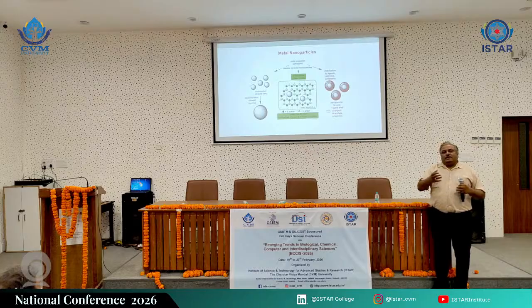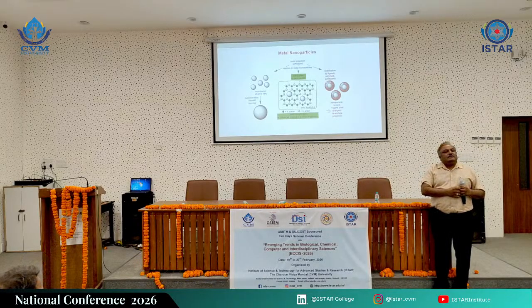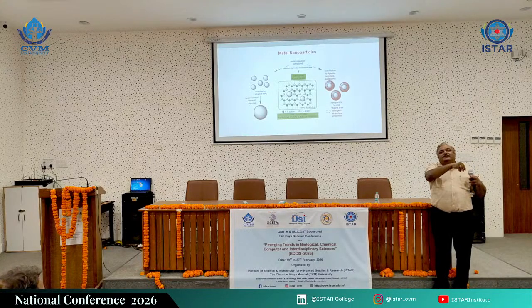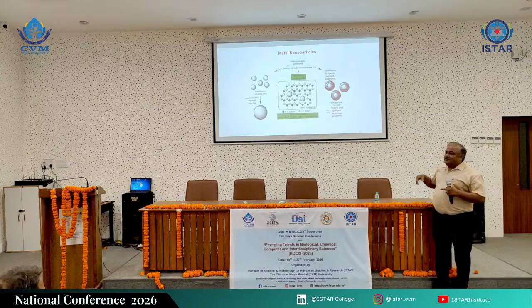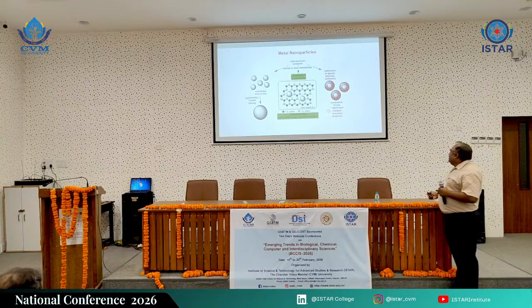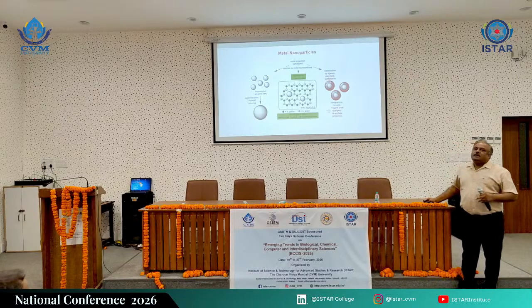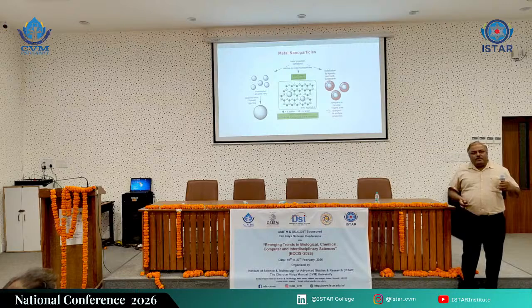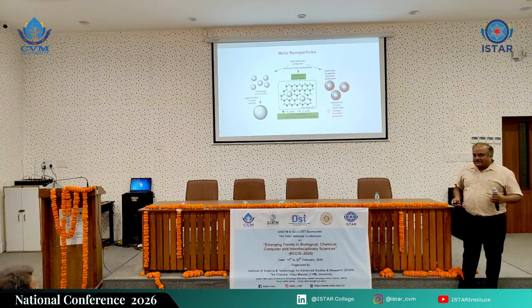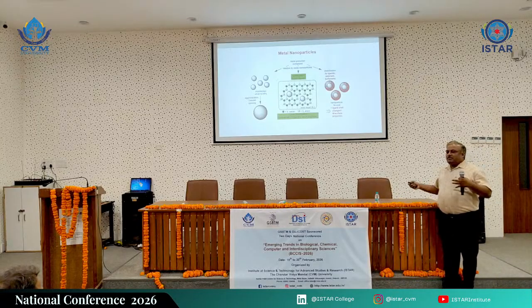Say for example, any metal oxide has a tendency to bind carboxylate-containing groups. So if I use oleic acid coated on iron oxide nanoparticles, then it will be a permanent coating. It will not be detached, because with the iron hydroxide defects on the iron oxide nanoparticle, it will go and bind permanently. So oleic acid will be bound like this and it will not fall apart. So there will be a permanent coating. It will not allow the nanoparticles to agglomerate, and the size control will be done. These exercises are basically done to control the size, because as soon as you allow them to agglomerate, they will go out of the nano domain and be in the micron size or sometimes even larger, depending on how long you allow them to agglomerate.